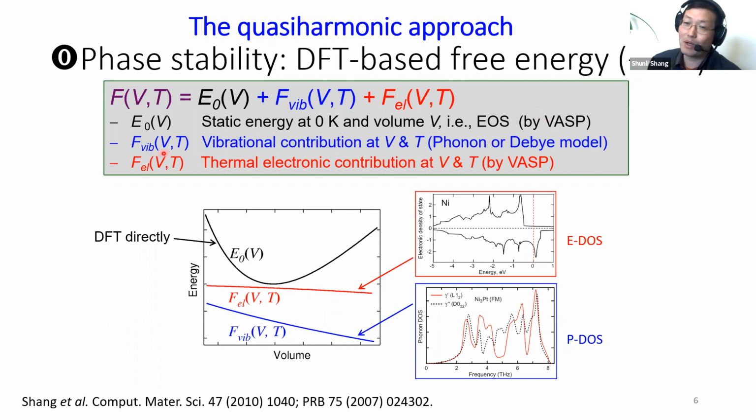The second term we call the vibrational contribution. It's a function of volume and the temperature. We can use the phonon calculation to do the prediction, or the Debye model. For phonon calculations, the input is only the phonon DOS, phonon density of states.